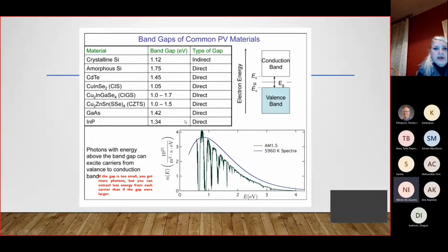And now we will explain why we choose exactly these band gap values, or why these semiconductors, or other semiconductors which also have a band gap in this range, are really suitable. For instance, for silicon, from 1.1 eV and higher energy, you have a large enough number of photons with enough energy to cause the photoelectric effect. If you choose a band gap that is too high, outside this optimum area, then the number of photons which can cause the photoelectric effect will be too small.